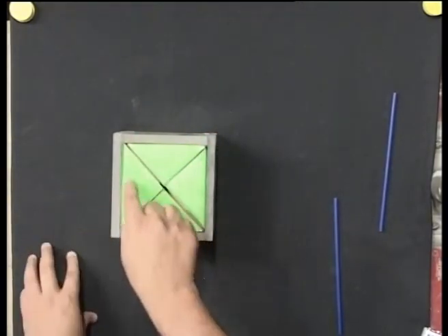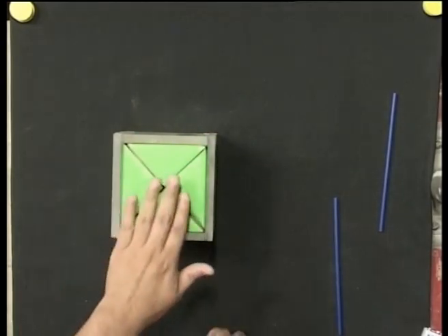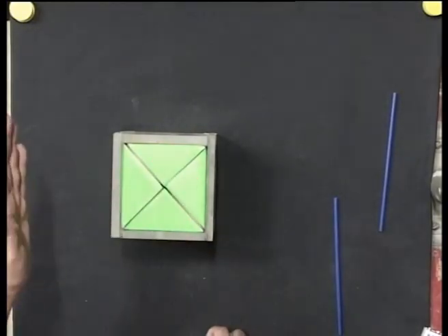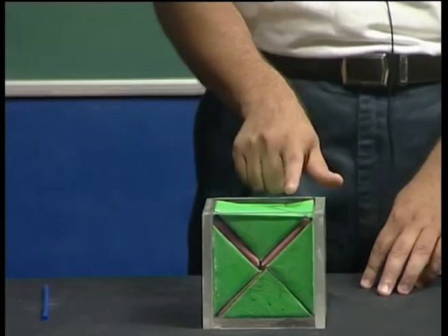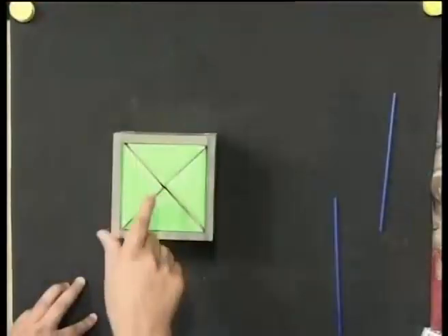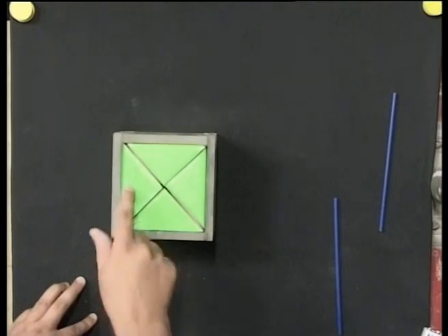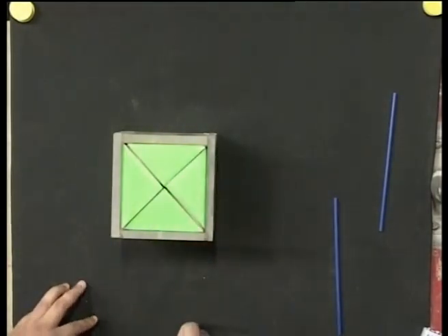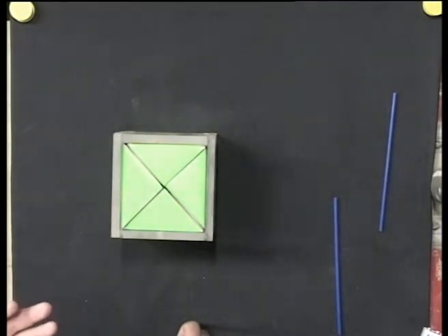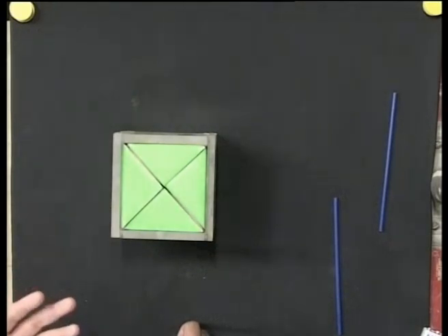So particularly, suppose I take this octahedral void, it is shared between this unit cell, the unit cell above it, the unit cell to the left of it, and the unit cell below that. So it's shared between 4 unit cells, and therefore the contribution of this octahedral void to this unit cell is just 1/4. So since I have 12 edges, 1/4 into 12 is 3, plus 1 at the body center, therefore there are 4 octahedral voids per cell, which matches exactly with the number of atoms in the cubic close packed structure, which is 4.